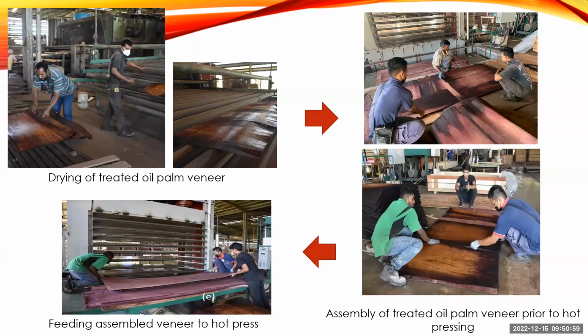This is after treatment. We will dry the treated oil palm veneer by passing it through veneer dryers to slightly reduce the moisture content to around 20%, so that during hot pressing, blistering will not occur.